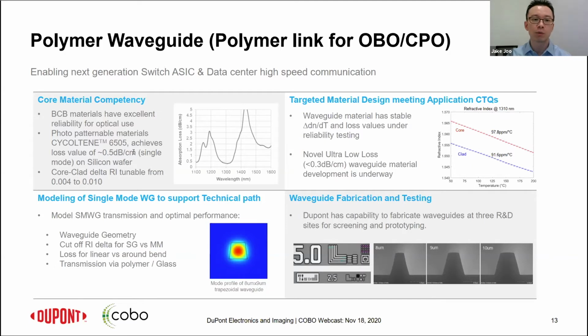With Cyclotene material 6505, we were able to demonstrate the material itself has low loss, about 0.3 dB at 1310 nanometers. And at the system level, the waveguides we fabricated so far have roughly 0.5 dB. And it's rock solid even at high temperature, total reflow conditions as well. We can also change some of the clad formulation to adjust the refractive index based on customer requirements. We also see that dn/dT, the temperature-dependent refractive index, is critical because that can also change the coupling behavior. And it is consistent over a broader range of temperature, meaning that it'll still guide as a single mode as necessary. From the fabrication perspective, we are also able to demonstrate down to around 5 microns, and generally make it in the 8 to 10 micron range.